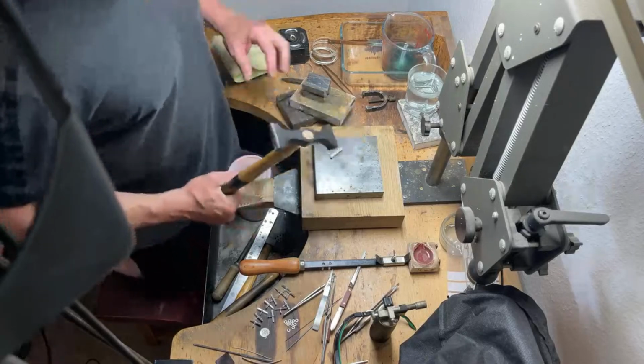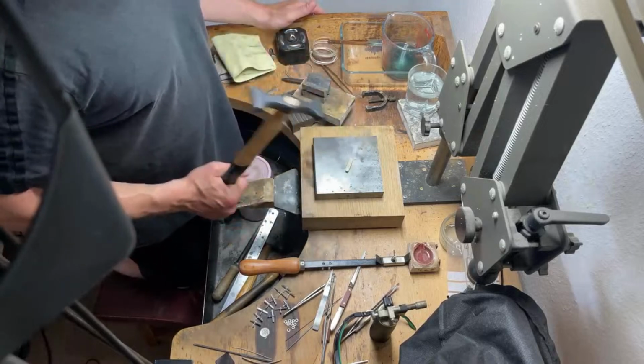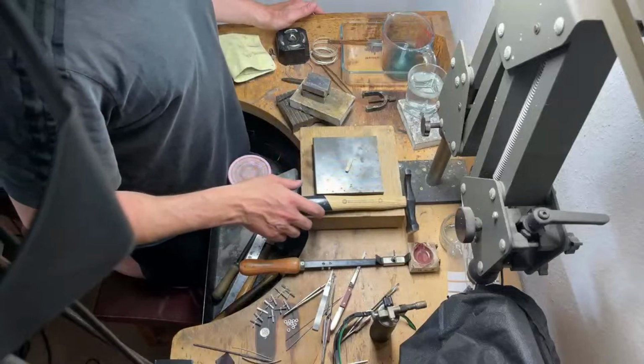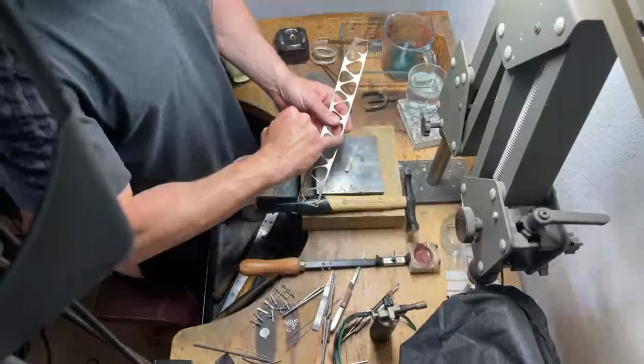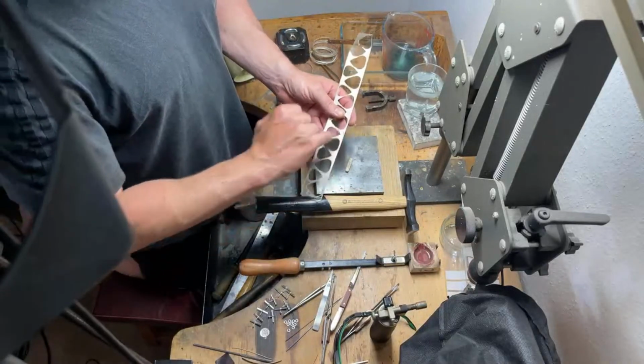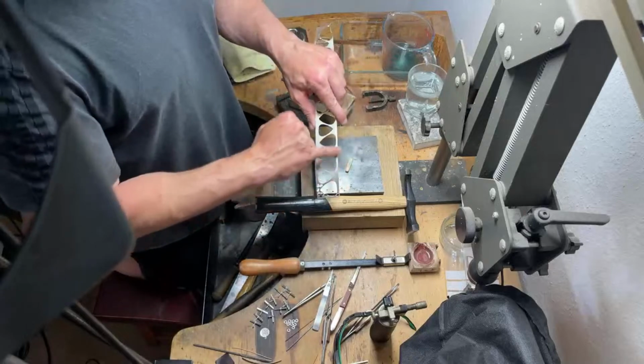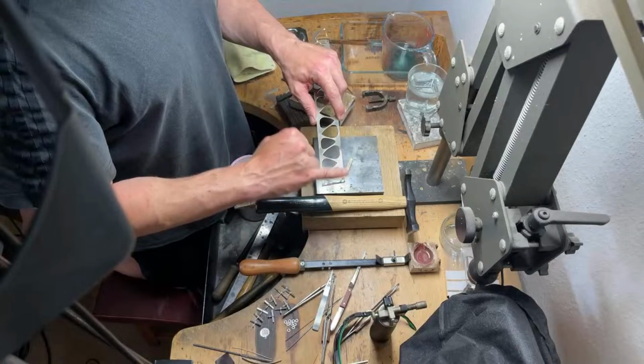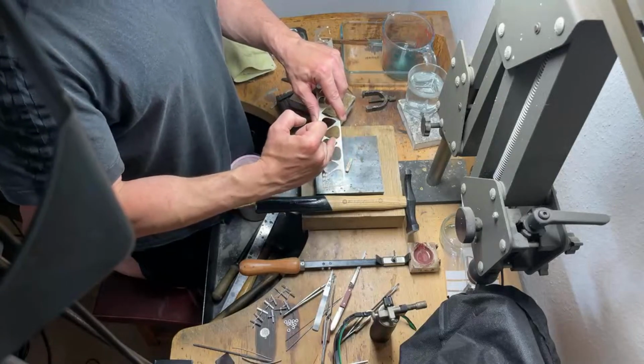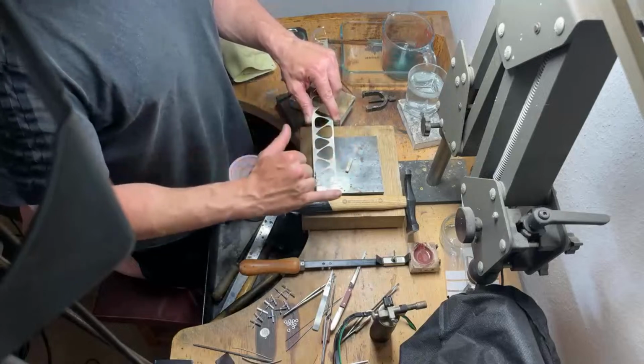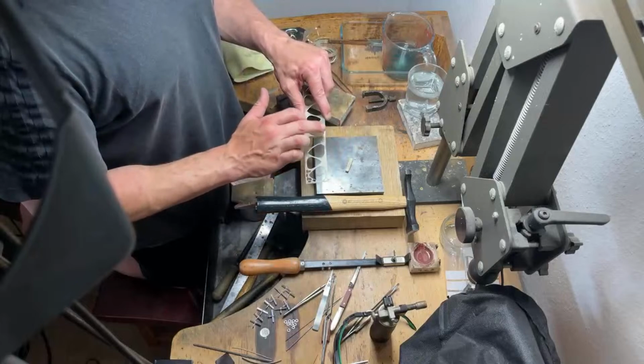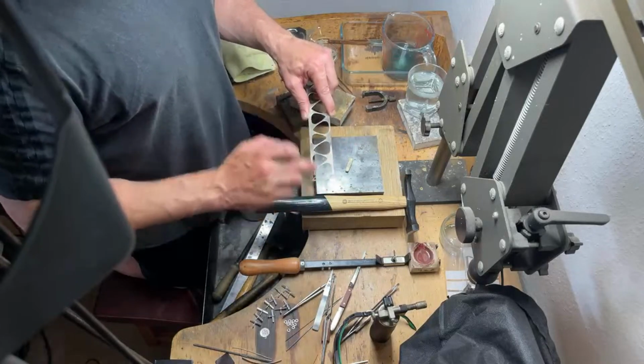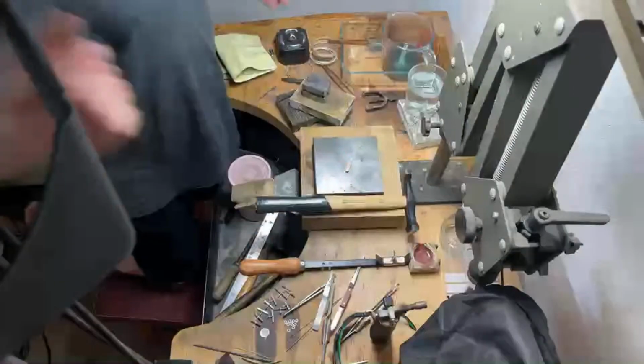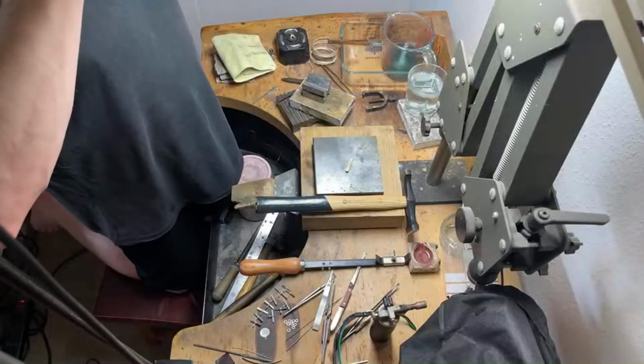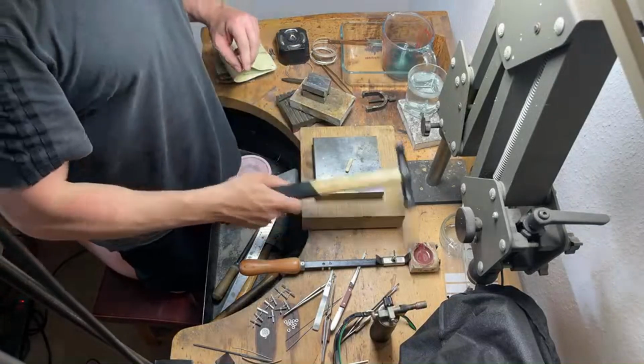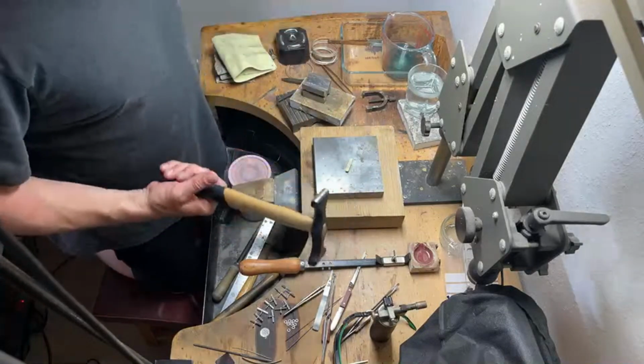Right. So the peening. I think peening is more important with flat sheet than with wire. With flat sheet, if you don't peen it, you get really bad cracks along the edge when you're rolling it out, regardless of the quenching process. The peening seems to drastically reduce the amount of cracking along the edges, so you get more usable metal. I'm not sure what it's doing to the wire ingots, but it's definitely helping. But again, because there's no info, I don't know how much we're supposed to do.